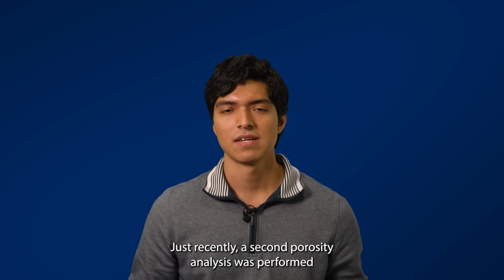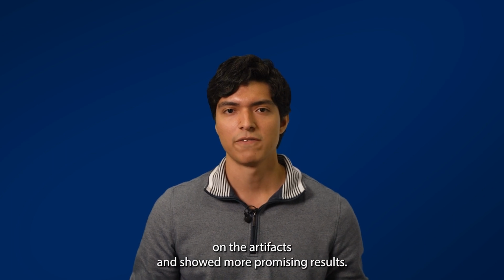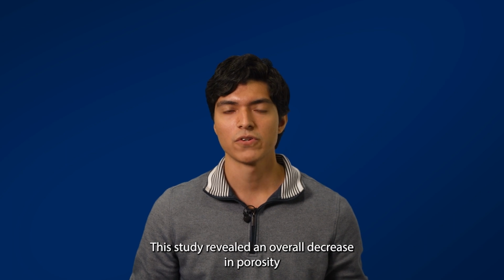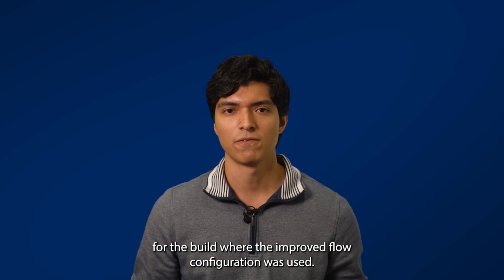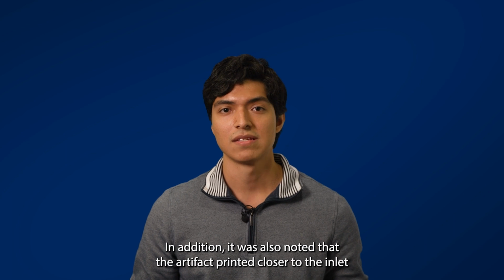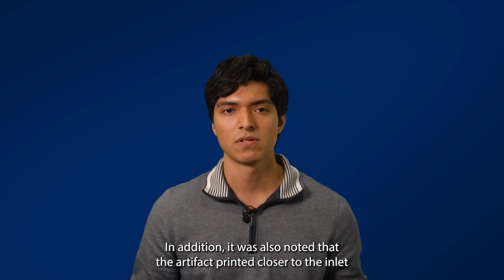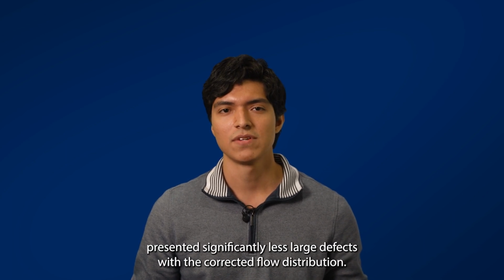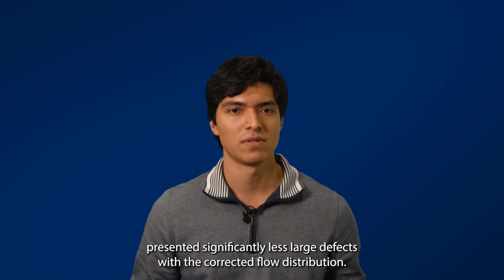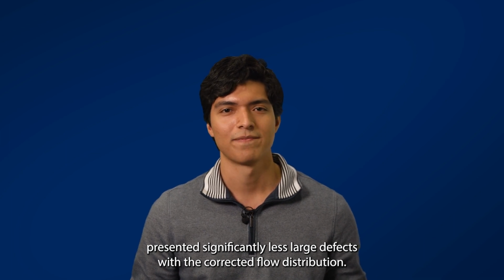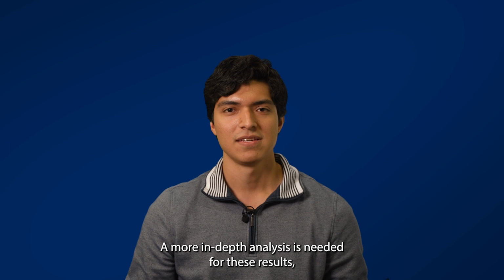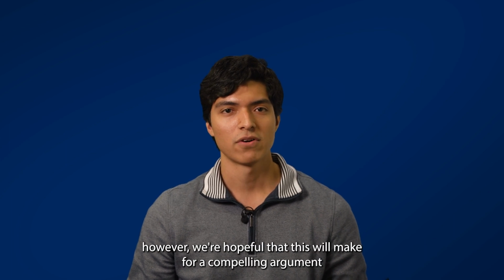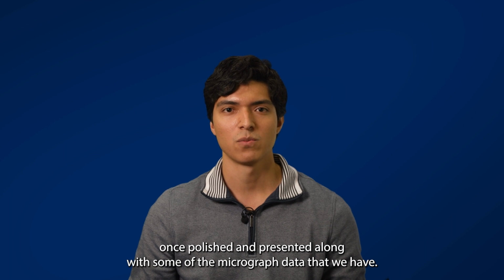Just recently, a second porosity analysis was performed on the artifacts and showed more promising results. This study revealed an overall decrease in porosity for the build where the improved flow configuration was used. In addition, it was also noted that the artifact printed closer to the inlet presented significantly fewer large defects with the corrected flow distribution. A more in-depth analysis is needed for these results. However, we're hopeful that this will make for a compelling argument once polished and presented along with some of the micrograph data that we have.